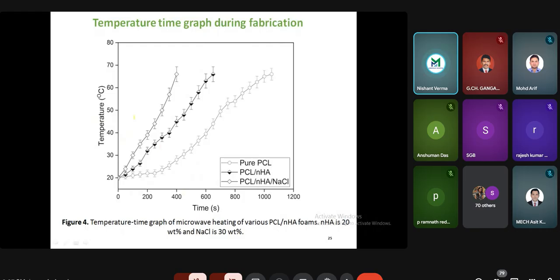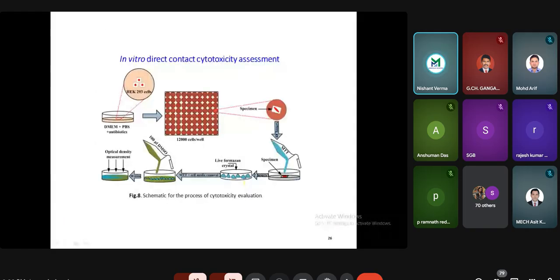In the temperature-time curve, we can see the case of pure PCL, polycaprolactone, the case of the composite, and the case of the material where the NaCl was there. You can see in that temperature-time curve how rapidly it is heated. All of this data has already been published by us in several journal articles. After that, we made the composite.